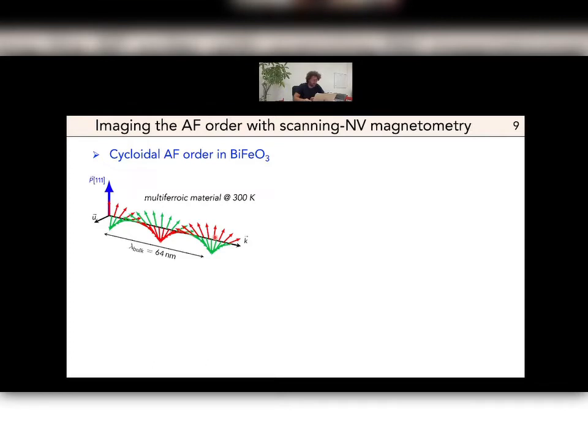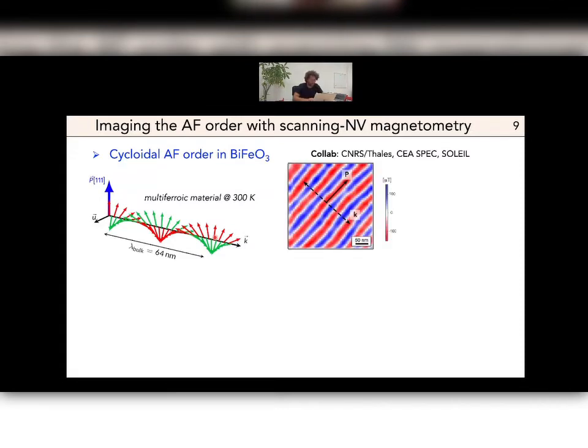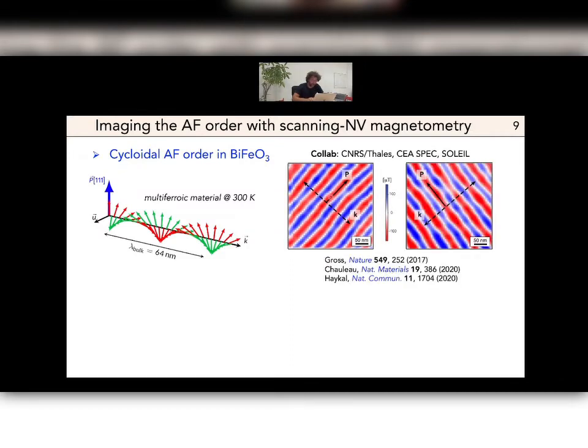We first started a few years back to try to image this kind of cycloid in bismuth ferrite, and this is a typical result that we got a few years ago. You see indeed that there is a magnetic field modulation with a propagation vector k that is perpendicular to the ferroelectric polarization. But what is nice here, besides being the first time that this kind of cycloid is observed in real space, is that if you rotate the polarization with an electric field, then you can verify that you can also rotate the magnetic order thanks to the magnetoelectric coupling.